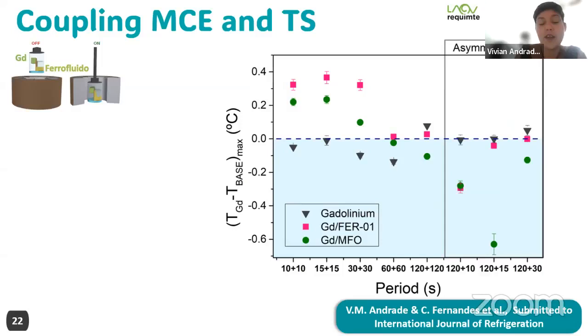Yes, it's small. It's 0.6 Celsius degrees. However, it's half of the theoretical one. The theoretical one for the system using two thermal switches was 1.12 Kelvin. Celsius degrees, it's a difference of temperature. So a temperature span of 1.12, and here we have a temperature span of 0.6. So if we consider the losses from the environment, we have a quite good temperature span.